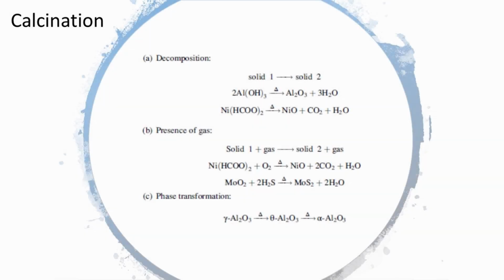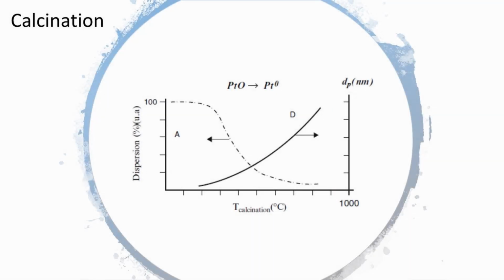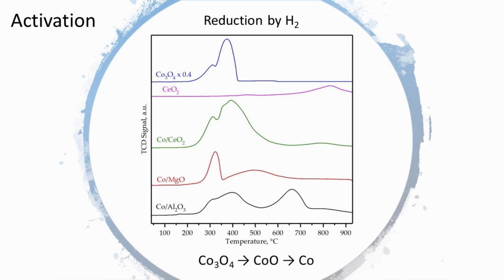After impregnation and drying, the catalyst precursor is usually calcined, that is, heated in air. Calcination, or more generally thermal treatment, is carried out to decompose the metal salts and to convert the metal salt into metal oxide. Depending on the nature of the nanoparticles required for the catalysis, a further activation step may be needed.